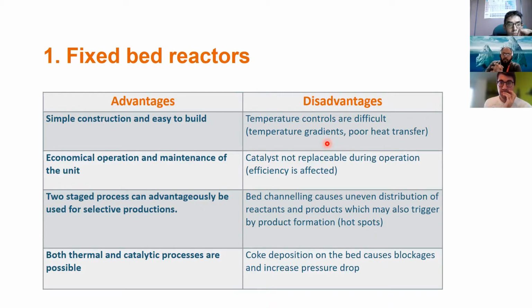Bed channeling means that the product can just channel in the bed. It is not distributed, which can also trigger some hot spots in the channels, or can lead to secondary reactions forming char or coke. And then there is coke deposition on the bed, which forms a blockage on the bed, which means that it will increase the pressure drop in the system.